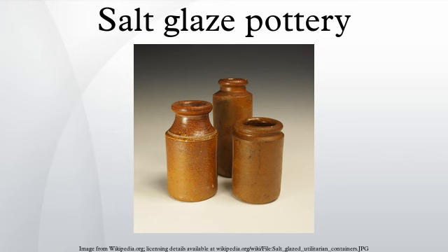Process: the salt glaze is formed on the unglazed body by reaction of common salt with the clay body constituents, particularly silica, toward the end of firing. The body should ideally be richer in silica than normal stoneware, and iron impurities can help produce good salt glazes. A reduction atmosphere can be employed as the reduced iron silicates are very powerful fluxes.